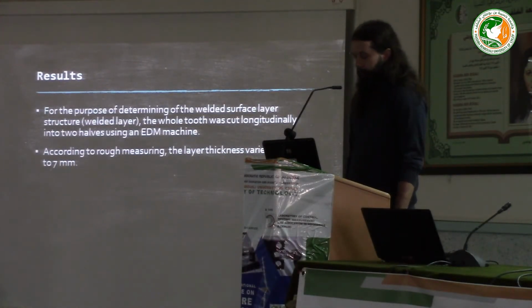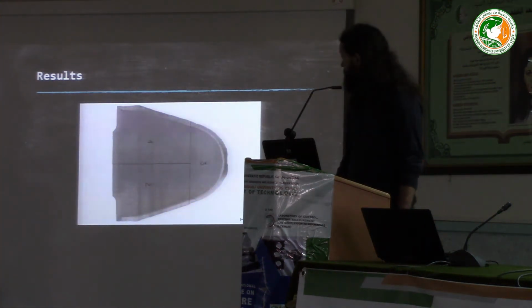Now, in order to determine the macro and micro structures of the surface or the welded layer, the tooth was cut longitudinally into 2 halves using an EDM machine. And the rough measuring determined that the layer thickness ranged from 3 to 7 millimeters, 3.1 to 6.4 more accurately. And here you can see one of the halves that was used.